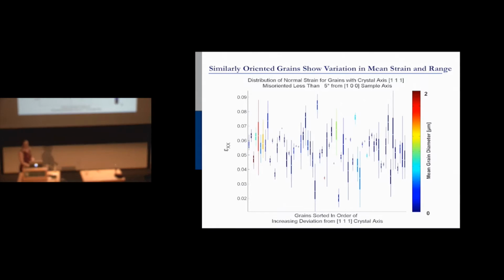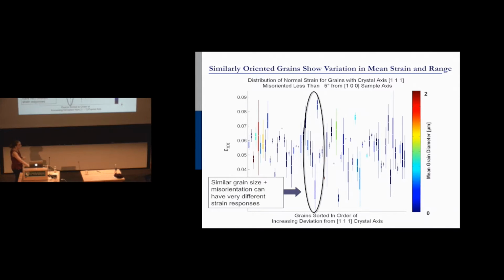You can't predict. It's not reasonable to predict in modeling how much a grain is going to transform by having similar orientations, and you do have to consider the neighborhood. Here, you have very similar grain size. They're all blue. You have incredibly similar orientation, right? They're all within this tiny little angle of difference from each other. So they're the same size, they're all pretty much dark blue, they're the same orientation. They're all pretty much exactly the same type of grain, and they're totally different from each other.